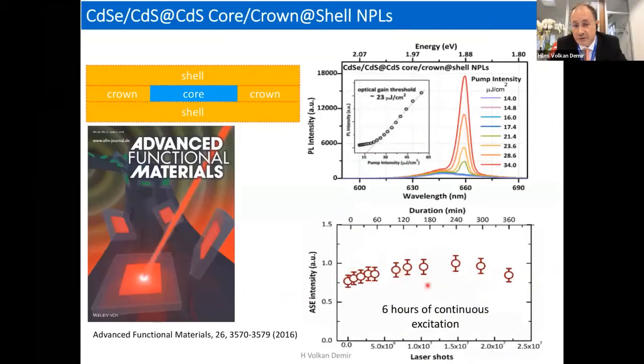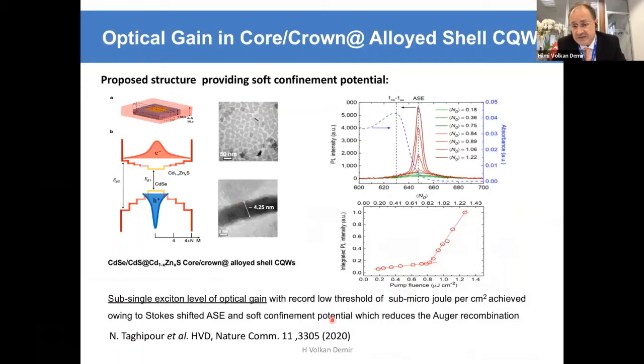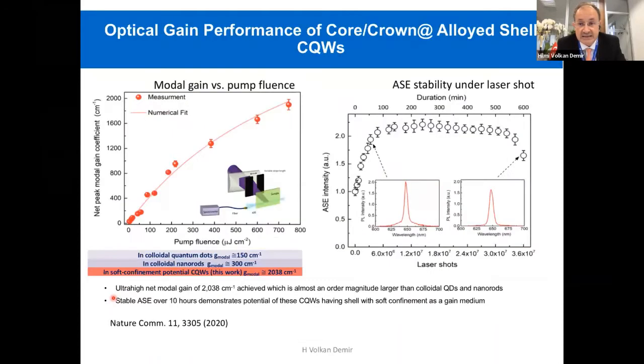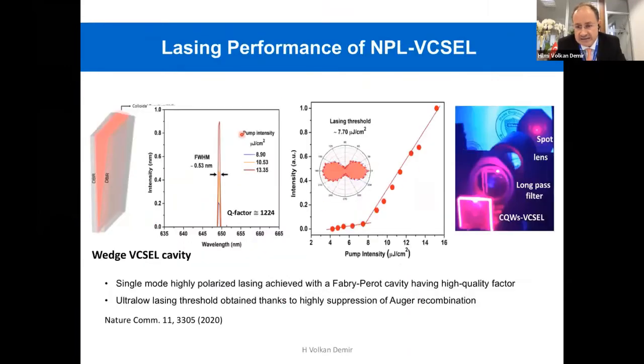We can use them continuously for long hours with some special designs as shown here. You see here a three-dimensional structure. We start with the core, first do the crown, periphery passivated, and then shell coating everywhere. We can push these results. These are really quite recent, disseminated in Nature Communications, showing that you can engineer even better. In this case, you can go to an unprecedented low level of excitation to observe gain. This is per particle on average less than one single exciton, meaning one electron-hole pair. And this, of course, being a physicist and electrical engineer, is really exciting. We can push these results to show long hours of operation and lasing performance.